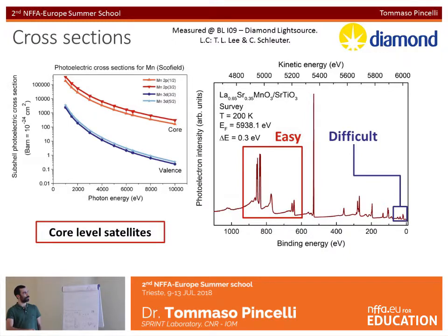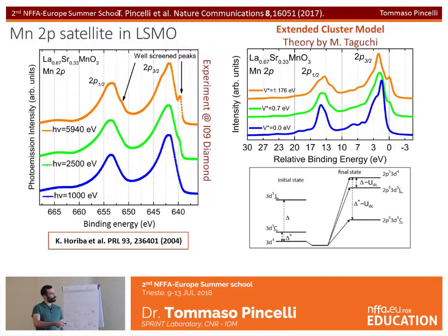So you can look at the satellites of the core level peaks, and if you increase the photon energy and you reach the region which is metallic, then you see a satellite appearing in the manganese 2p peak that arises from the fact that electrons in the bulk are able to move more freely and thus are able to screen the core charge that we created by ionizing. And so this new mechanism for screening the charge appears only in the bulk, and thus we see a new satellite appearing when we increase the photon energy.